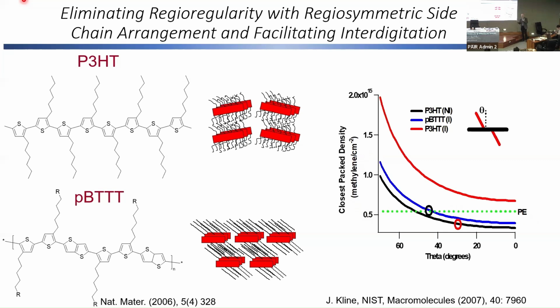So what that tells us is that it's not possible for P3HT to interdigitate. So you have to think about these lamella as floating on top of each other. They don't actually come together. And when they don't do that, you can't get a three-dimensional crystal. You can only get one sort of lamella, like a sheet flapping in the wind. And if you were to press the sheets together to form a book, there would be no order in the vertical direction. And we thought about that, and we developed this polymer called PBTTT. And you can see it's very simple changes we've made here.